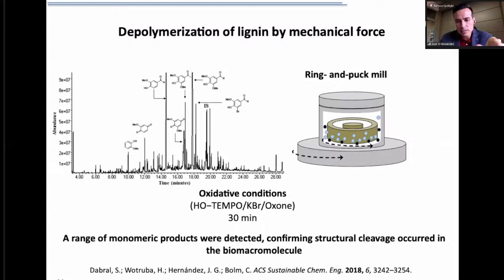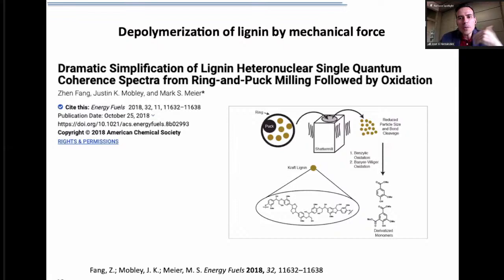And a few months later, we saw a paper from some colleagues in the US who also observed independently that indeed there is a simplification, they call it, in the structure of lignin when it is ground under oxidative conditions. However, the conditions were different. The only thing that was the same was the type of mill, because this is not a ball mill, remember, it's a ring mill.